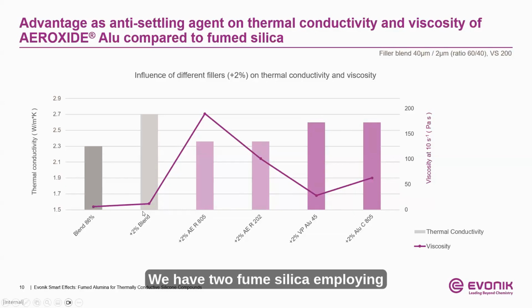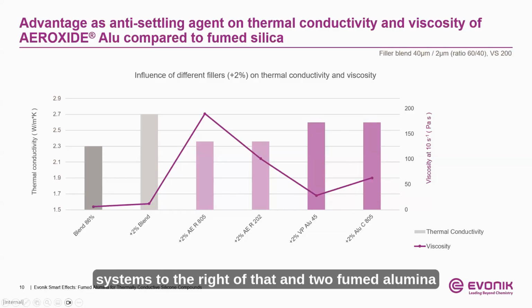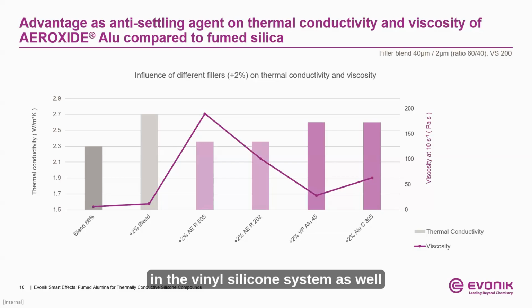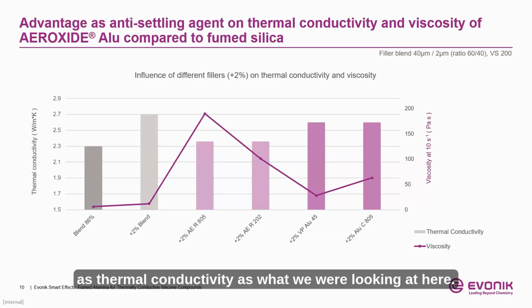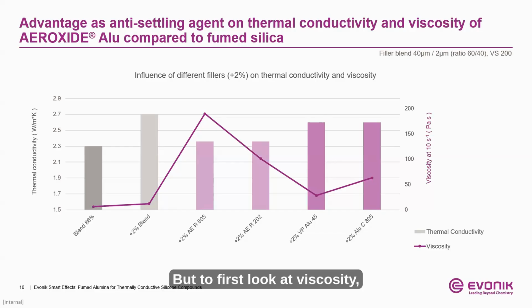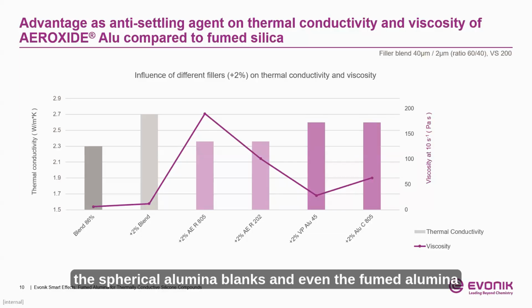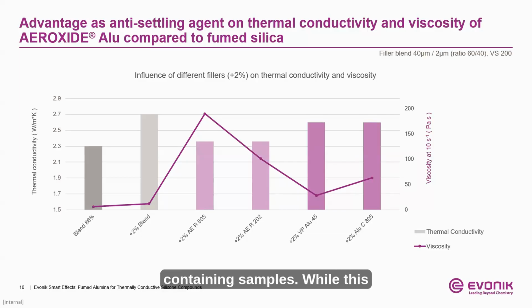We have 2 fumed silica employing systems to the right of that, and 2 fumed alumina employing systems toward the end of the graph. Again, focusing on viscosity generation in the vinyl silicone system, as well as thermal conductivity, is what we were looking at here. But to first look at viscosity, we will look at the fumed silica, the 2 samples in the middle, the R805 and the R202. Note the considerably higher viscosity in this system versus the spherical alumina blanks and even the fumed alumina containing samples.